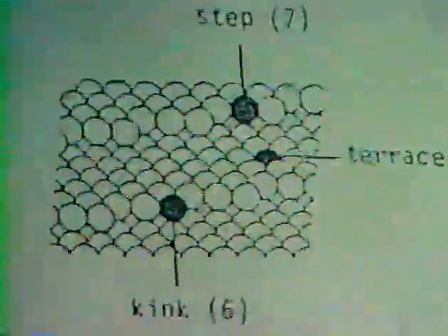And this nomenclature comes pretty much from the work of Somorjai and his colleagues, and you can see the same sort of things. If you take a single metal crystal and you slice them at different angles, you can produce either just edges or you can produce a lot of kinks, which are corner type atoms. Now, real catalysts that are used in the industry don't look like that, but they're tiny little metal particles.